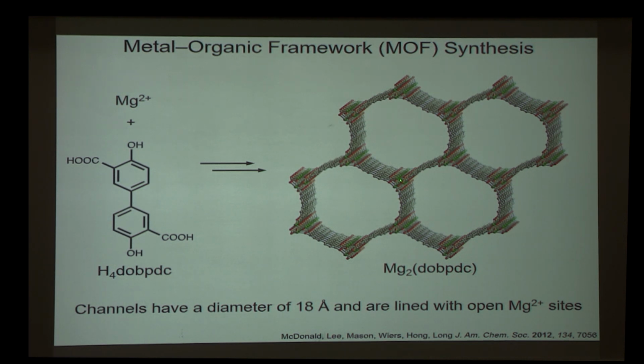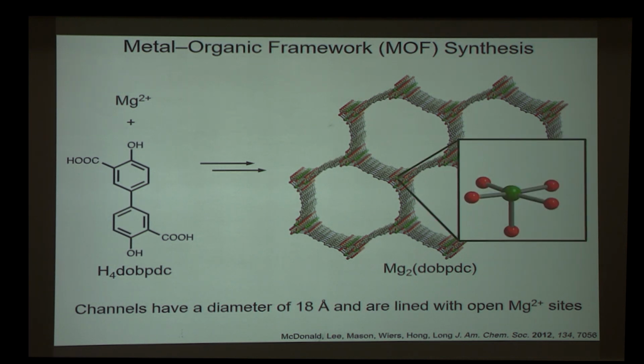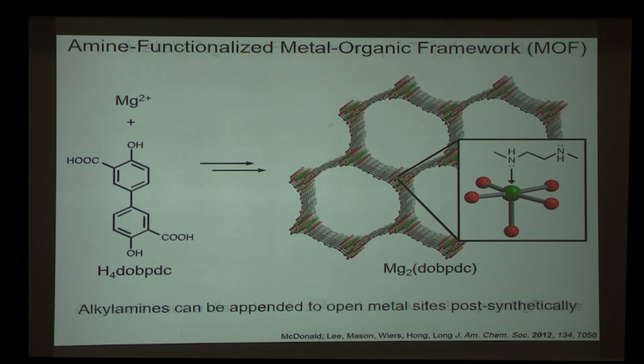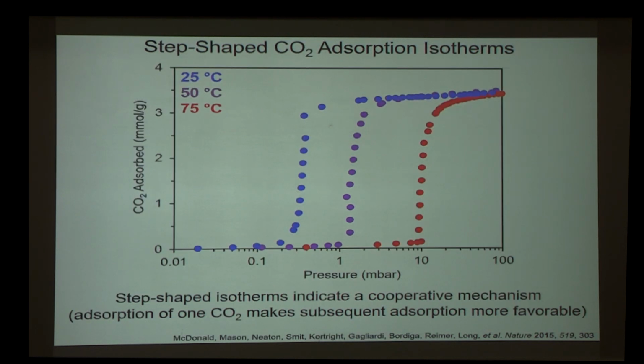And each corner of the hexagon is lined with metal sites having this coordination environment, where there are 5 oxygens contributed from the organic linker. And there is a 6th site that we can post-synthetically modify with a diamine. Here, one of the amines coordinates to the metal, tethering the diamine to the framework. And the other amine is dangling in the pore. These materials exhibit some remarkable properties for CO2 capture.